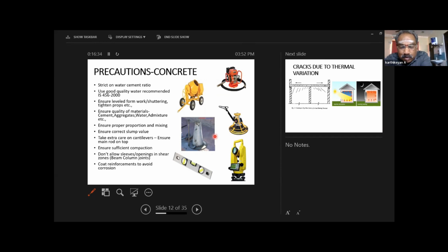If the slump values are within limit as per IS 456 or as per the concrete technology book, then only is there proper workability and can the water cement ratio be maintained. Due to improper slump, there is a chance of segregation and cracks. So the slump cone is the most important instrument while making concrete. People do cube strength tests nowadays because of awareness, but people don't use the slump cone.